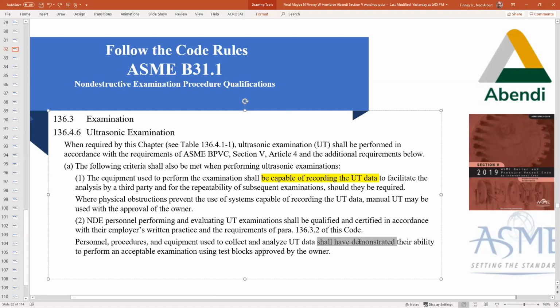NDE personnel performing and evaluating UT examinations shall be qualified and certified in accordance with their employer's written practice and the requirements of paragraph 136.3.2 of this code. Let me just highlight a couple of things that are key here. Personnel, procedures, and equipment used to collect and analyze UT data shall, not should, shall, it's mandatory, have demonstrated their ability to perform an acceptable examination using test blocks approved by the owner.